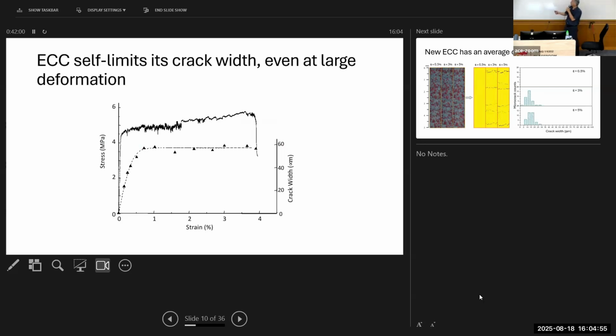Okay, so this is another actual test curve of a normal strength ECC. And you see the bumps going on. Every time there is a bump, it forms one of the micro cracks. So these micro cracks are very, very tight, and that's the reason why they are called micro cracks. And this curve here tracks the opening of one of these micro cracks.